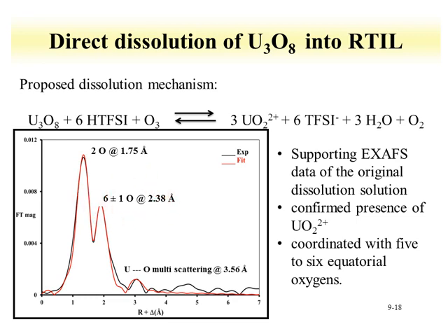So this shows that this reaction forms the oxidized UO2 2+ in the TFSI solution, and that any chemistry at this point is done with uranium, the uranyl. One of the issues with the uranyl is that we have oxygen present on that molecule, so reduction of this molecule on an electrode, we've shown that under certain conditions, can form uranium dioxide on the electrode surface.